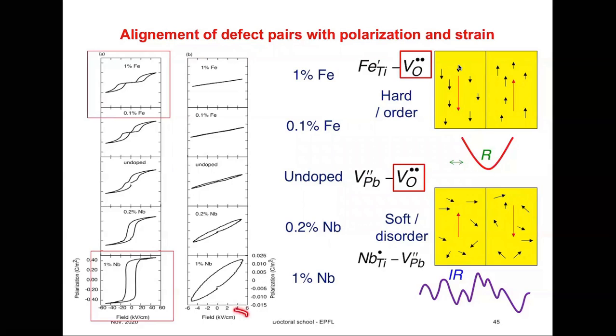So at weak fields and strong fields, we have very little domain wall motion in hard material, in acceptor doped material, and basically if you look at polarization as a function of electric field, you almost don't have any hysteresis. So if domain walls move, they move like a membrane and come back when the field is zero. So they follow exactly the same path. There is no stopping them in some intermediate position. The hysteresis is absent.